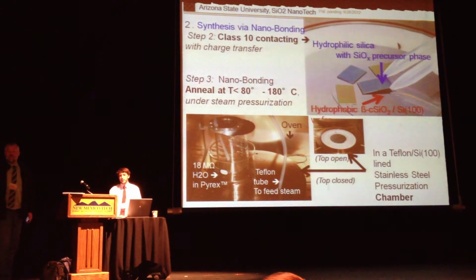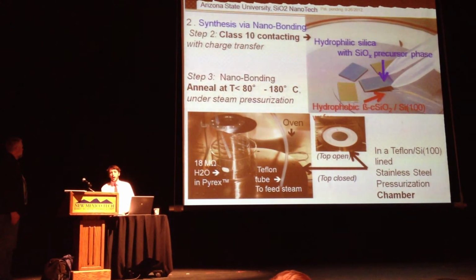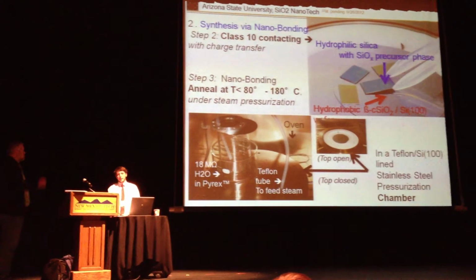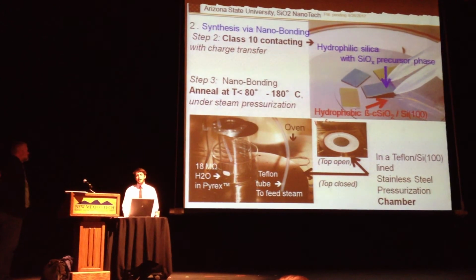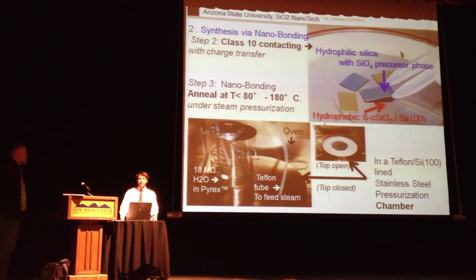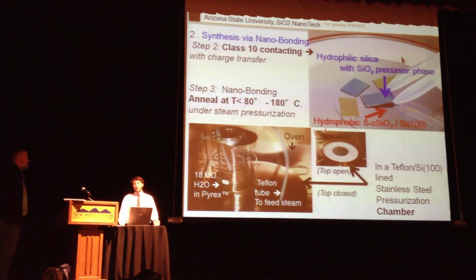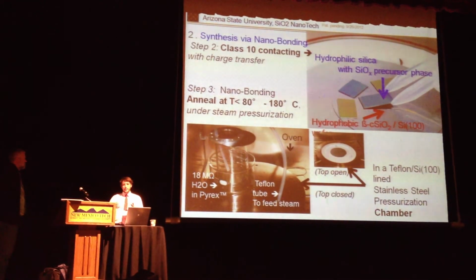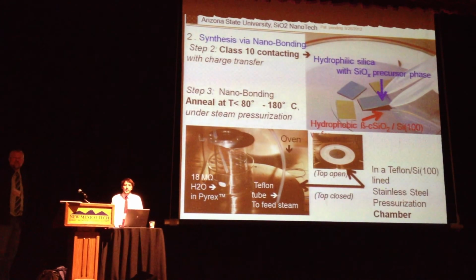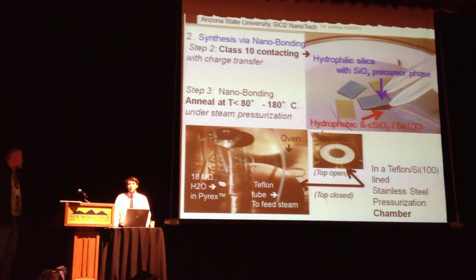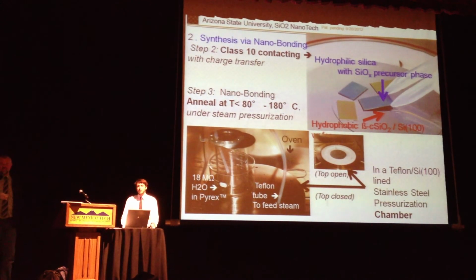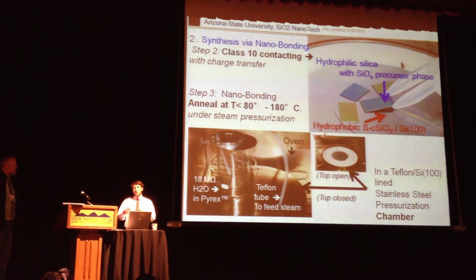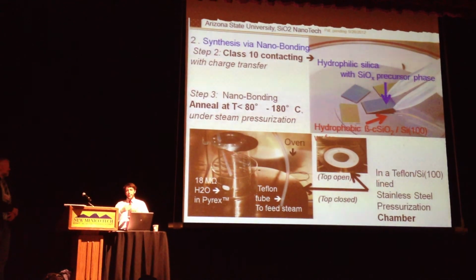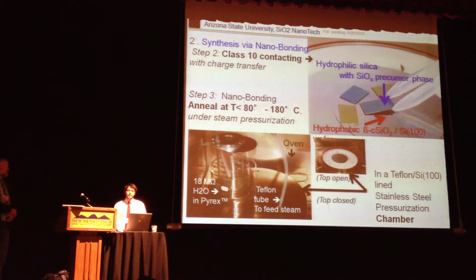The structure that you showed at the end, is this derived from some type of analysis or modeling or both? We've done some. Actually a grad student who graduated, his thesis was on the actual modeling of the stress on the silicon crystal that would occur, and the optimization and understanding of what that model has to be, and what the possible tensor stresses on the crystal structure are. The stresses were measured, or how was it? They were using a model on the crystal structure itself to understand what the stretch would have to be in order to bond those two together to make them match across the surface. So that was done by him, and the model is the best possible solution for what he was able to find. If I may just have a very quick follow-up question.